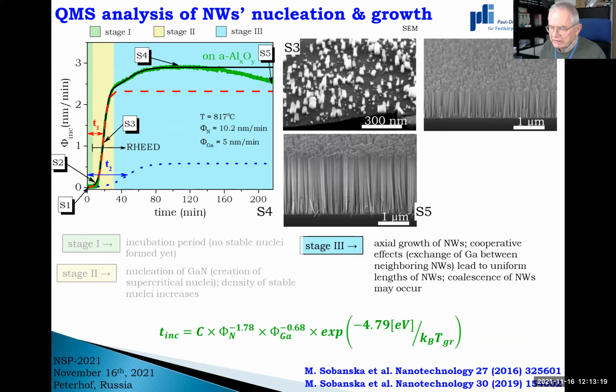We have explained what happens during coalescence. You know that if you take a nanowire, gallium sits on a top face and close to the top surface, because the diffusion length of gallium on a side wall is something like 40 nanometers. So all the rest desorbs. So the nanowire is covered with gallium on a top surface and on a periphery, about 40 nanometers long. Now, when you get into coalescence, you effectively reduce the surface available for gallium to sit. And this is what you see here. This is how we explain this in this paper. Yeah, it's perfectly clear. Thanks.